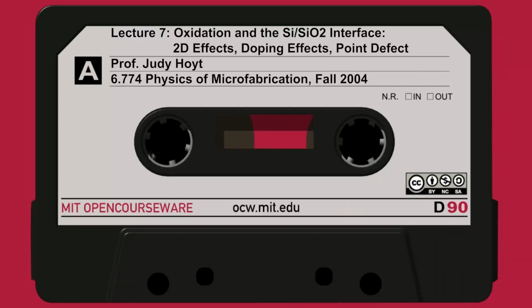This central region that's colored in gray, let's say that's my silicon pillar. And let's say I've grown a certain amount of oxide already. That's on this outer region. That's the oxide that I've grown. And now I'm just growing a little bit of new oxide. Remember, in oxidation, the reaction takes place at the interface, not at the surface. So to grow this little band of new oxide, let's say 10 angstroms, the oxidant has to diffuse in, has to react at the silicon surface, and then the new oxide has to push out on the old oxide to make room for itself. It's got to push up and push down and consume some of the silicon.